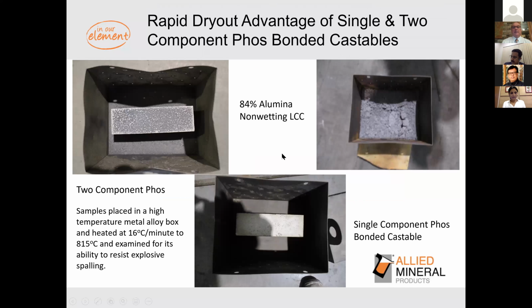I promised you we'd talk about the spalling. This is an extremely rugged test. The industry asked for 38 degrees C per hour ramp rates for dryouts. For the explosive spalling test, we ran it at 16 degrees C per minute ramp rates to 815 C. This is an excellent low cement 84% alumina non-wetting castable that we have put in all over the world. Works fantastic. But as you can see, because of the dehydration points of a castable, it will explosively spall. It will come apart.